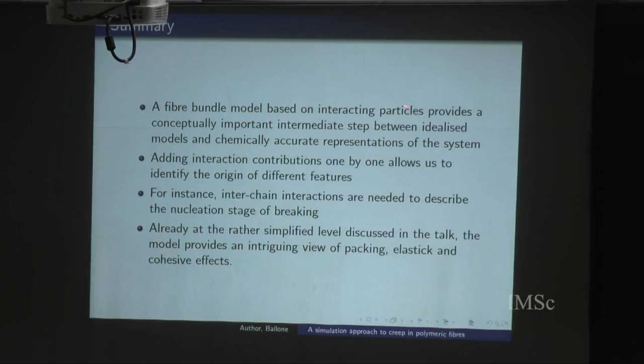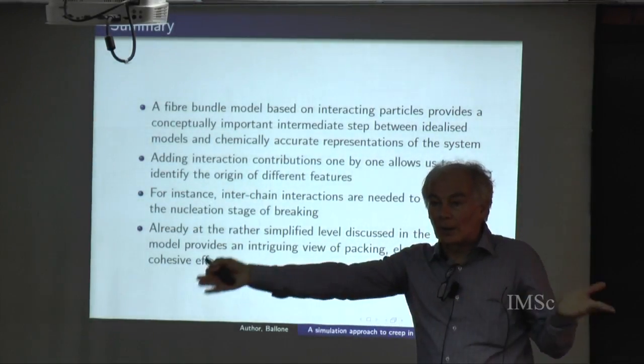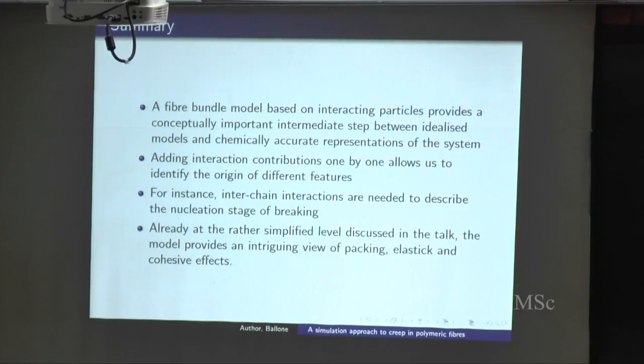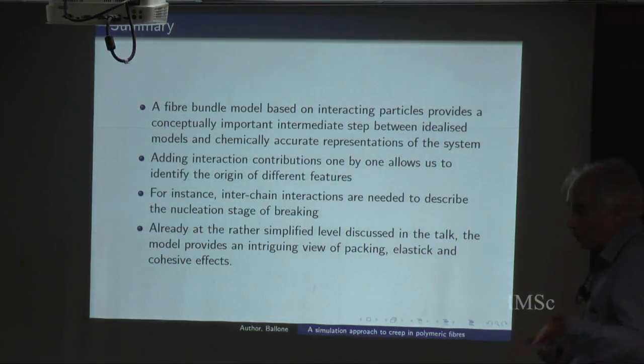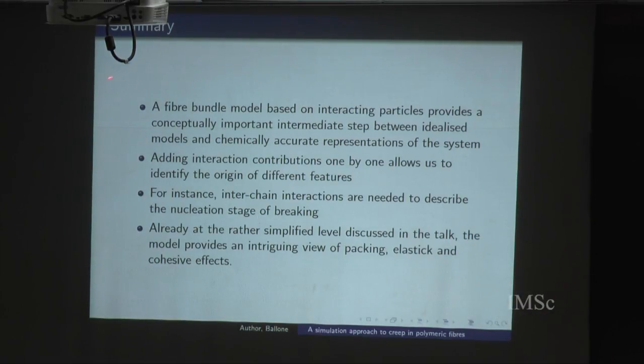So at this point, we are in the process of simulating a fiber bundle model based on interacting particles, and this is an intermediate step between idealized models and, next, a chemically accurate representation of a system using standard force fields modified just in such a way that they will break. Right now, most force fields don't break, they are harmonic. We will change that slightly, but LAMMPS, etc., already does more. So what we are doing is going from the most idealized to the more refined, adding contributions one by one, because we want to see what comes at each step.